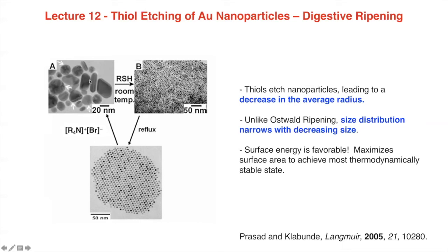So this interconversion actually looks like it's uphill to me. If you just have Gibbs-Thompson theory in mind, and you have a typical Ostwald ripening type of scheme in mind, this is going the wrong way. You shouldn't take a broad distribution of large things and make a narrow distribution of small things. This is disobeying one of the classical tenets of particle thermodynamics. And this is a reversible process too.